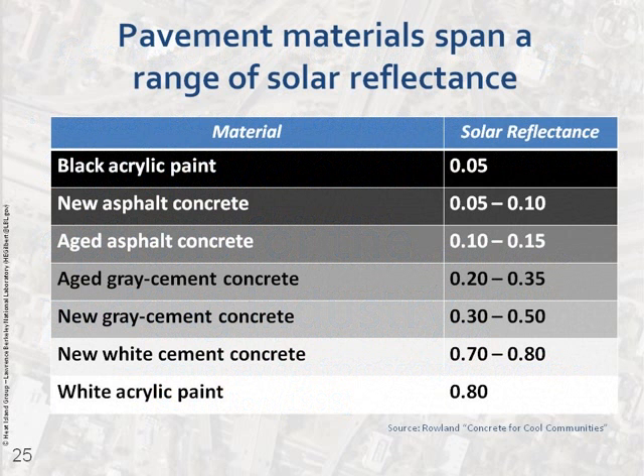Here again, we're just going to touch on solar reflectance. You can see, as Ben mentioned, new asphalt concrete has a range of solar reflectance between 5 and 10%. As it ages, it tends to lighten because the asphalt is actually oxidizing, so it can increase up to 15% depending on the solar reflectance of the aggregate or the rock that's exposed, right?